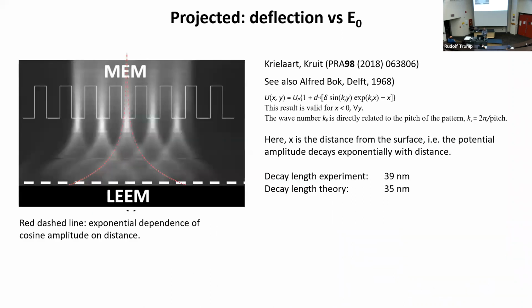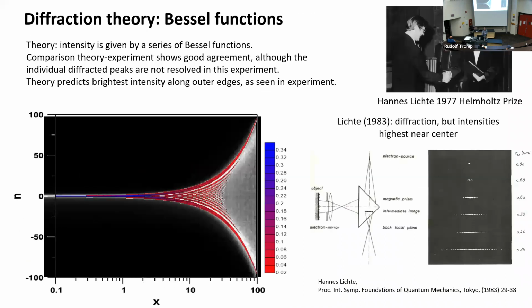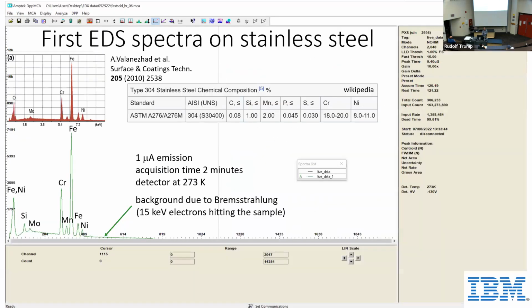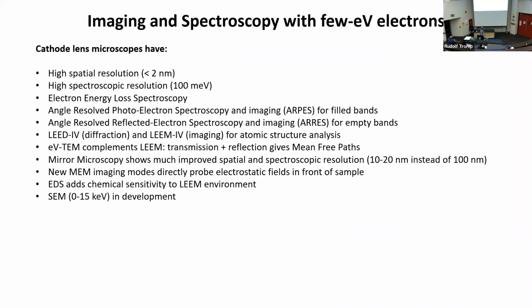All right, I think that's the last thing I wanted to say. I just skipped over the thing. We added elemental analysis using EDS detectors. We have high spatial resolution, high spectroscopic resolution, electron energy loss spectroscopy. You can look at filled bands using angle resolved photoemission inside the electron microscope, right, in the LEEM. You can look at unoccupied states by using this new reflected electron spectroscopy for the empty bands.